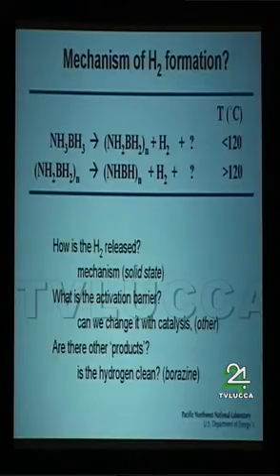So what the literature reports say is that there are two steps, and the nice thing is you can release the hydrogen in a couple of different steps. You can heat this up and release 6 weight percent in one step, heat it up again, and release another 6 weight percent. And there are some reports in the literature where you heat this up to over 900 degrees and you can release another equivalent. But we wanted to focus on accessible temperature ranges here, and so we looked at this in the scaffold material